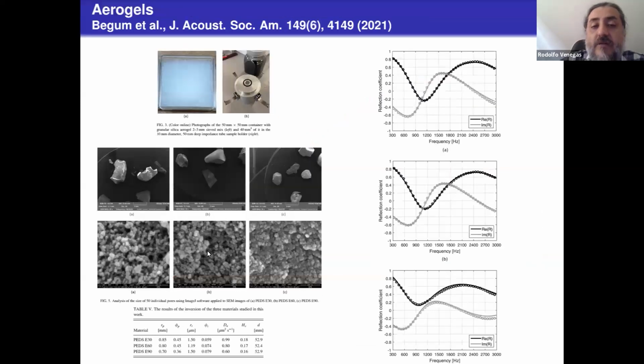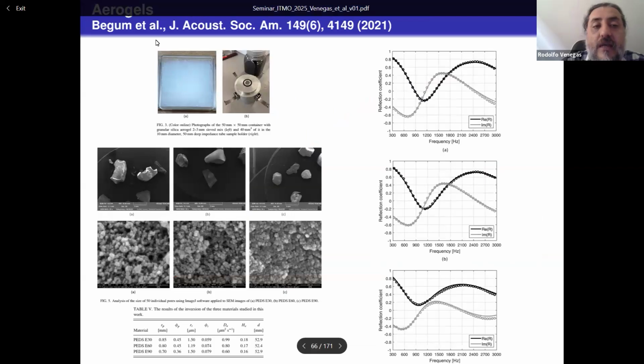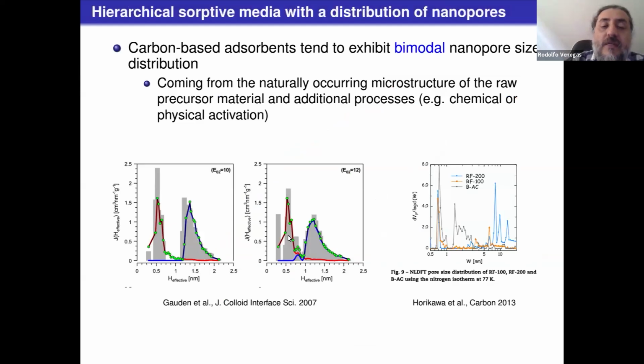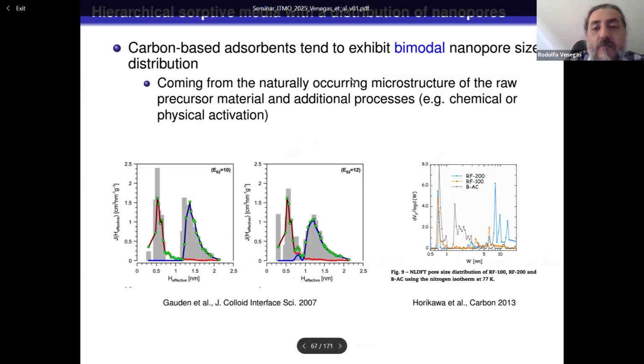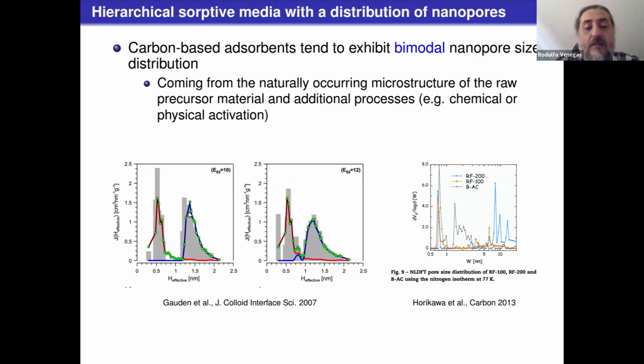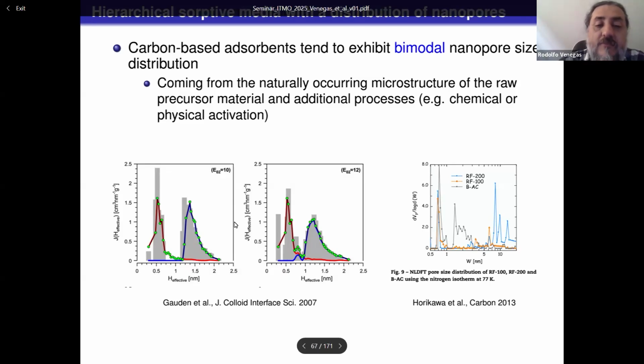We have applied the same model, but for other types of multiscale materials like aerogels, showing good agreement. And what we have been recently doing on this is to incorporate the effect of bimodal nanopore size distribution. So carbon materials tend to naturally have a bimodal nanopore size distribution. Some time ago, when we started this, we looked at these 2 peaks and said, well, 0.5 nanometers is very similar to 1.5 nanometers, so we will consider a single nanopore size. That's been proven a good approximation for many materials, but for others that might not be the case. And this is another example of the bimodal nature of the nanopore size distribution of carbonaceous materials.